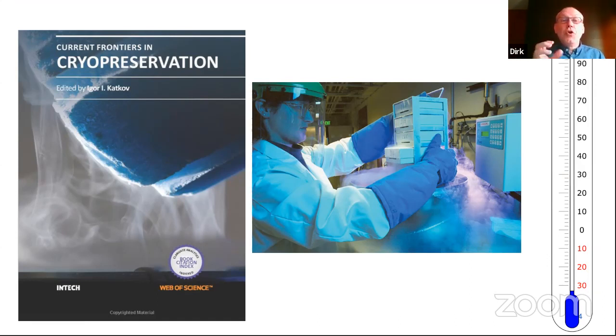We can check if the cold chain of this preserved sample has been broken or not, because if the temperature has increased from liquid nitrogen temperature to maybe -80 degrees centigrade, then the light of this persistent phosphor has escaped. If the temperature has remained low at liquid nitrogen temperature, then the light has not escaped. And so we can check in a very easy way, even after months and without using any additional energy, whether for this deep frozen sample, the temperature has ever, during this period, been increased to over, let's say, -100 degrees centigrade. And so this can be a very important application for really checking the quality of the cryopreservation, so the preservation of materials at very low temperature.